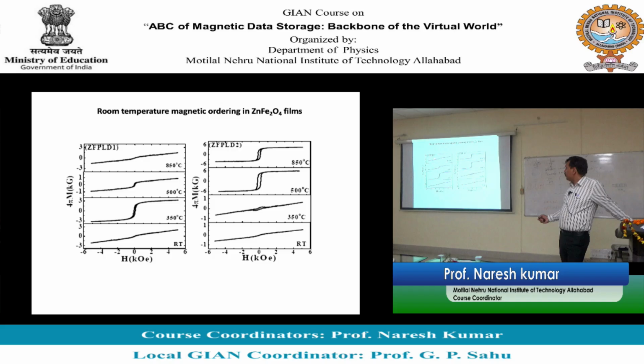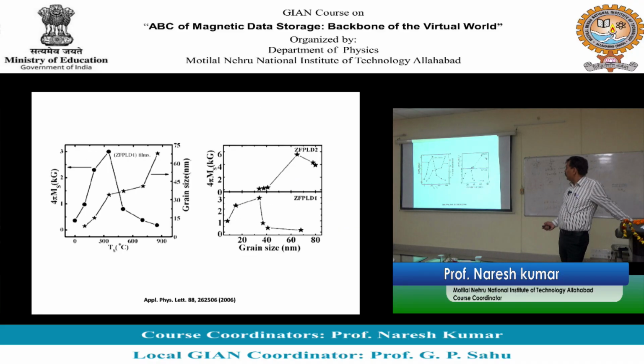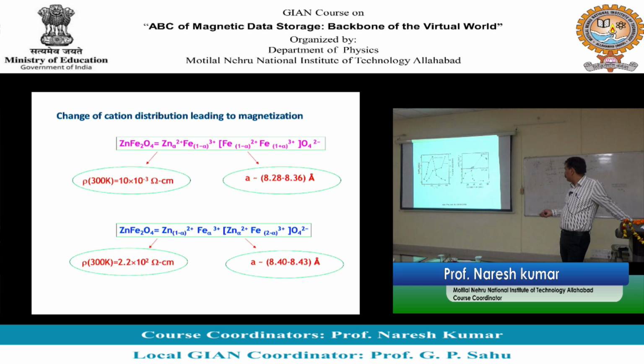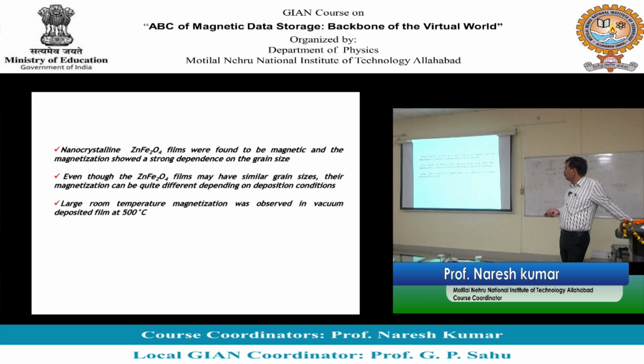See here, films grown in oxygen atmosphere at 850 do not show any hysteresis loop, but films grown in vacuum show a huge amount of magnetization in the film, right? And there are other associated magnetic properties that have been studied. We did it about 20 years ago. And this could also be verified by looking at the conductivity that we measured. So yes, zinc ferrite you can deposit by PLD, showing outstanding properties. Zinc ferrite, which is not magnetic in bulk, was magnetic and has a very good magnetic moment.